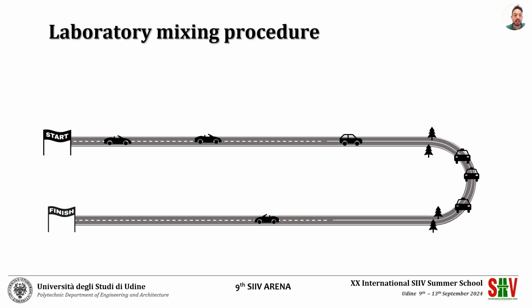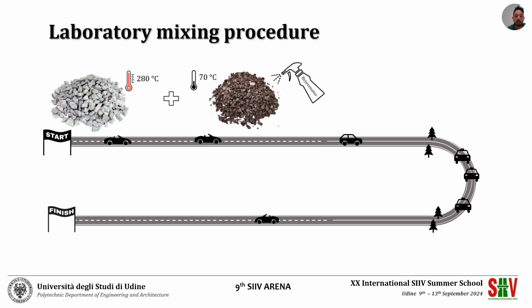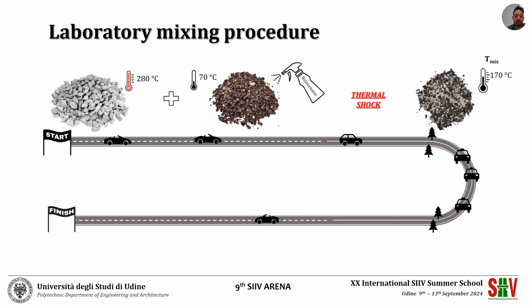A key aspect in the study was to find an appropriate laboratory mixing procedure mimicking the steps occurring in real asphalt plants. Virgin aggregate was heated to 280 degrees centigrade, meanwhile RAP was heated to 70 degrees and the rejuvenator was sprayed on it, leaving it sufficient time to penetrate inside the RAP, restoring chemical and physical structures of aged bitumen. The contact between these materials produced a thermal shock, allowing both to reach the desired mixing temperature set equal to 170.